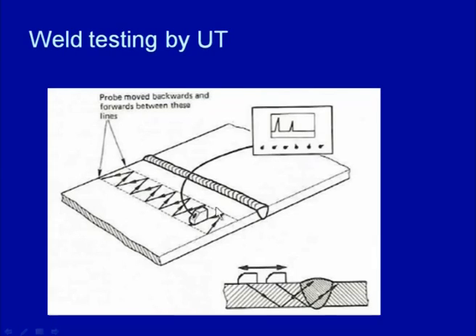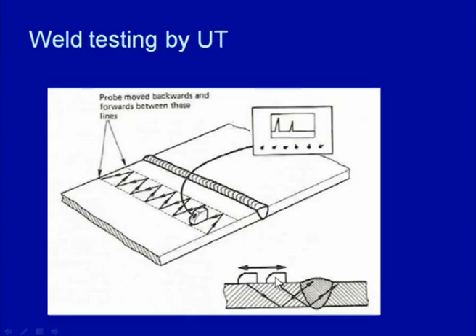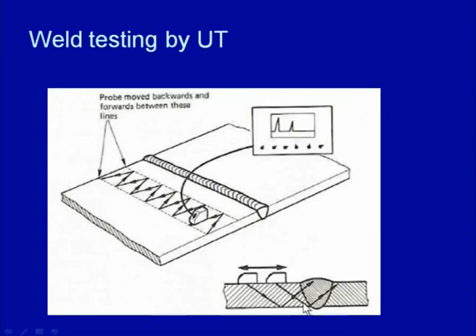Now, for conducting the UT test on the weld joint, a very specific pattern of movement is used. Here, say we are using either a 45° or 60° probe, depending on the type of probe being used, it will direct the vibrations at a certain angle. These will be transmitted, and then reflected back first from the bottom surface, then reflected back from the other side.